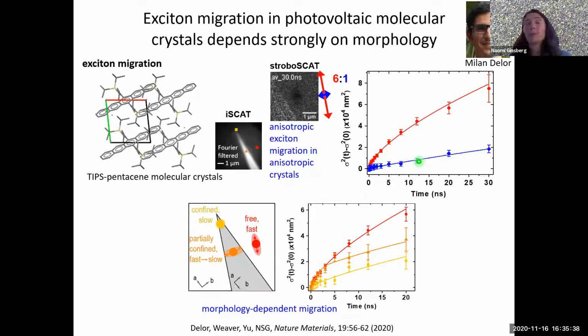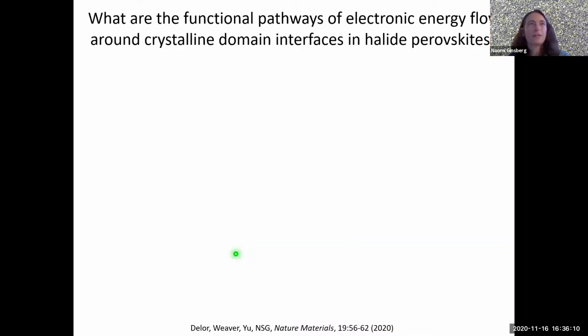What's more exciting to me about this is that not only can we measure it at that one location, but if we look at, say, the apex of this domain where there are grain boundaries, then we see much more compromised exciton migration. And even more interestingly, we see this piecewise behavior when we look at a region that's less confined by the grain boundaries, showing spatiotemporal evolution really clearly. So that's just a quick example to get us calibrated.